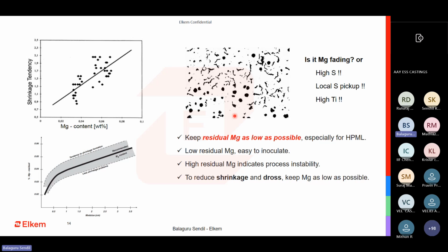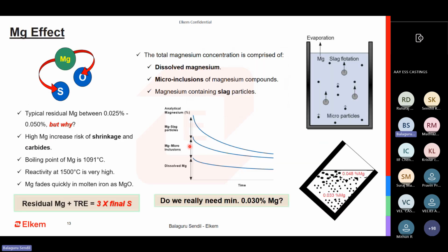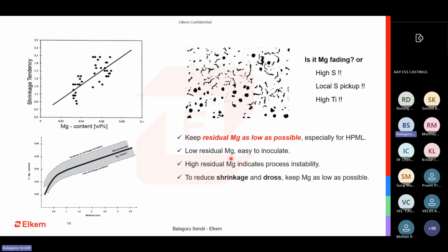It is quite stable. In the previous slide I showed, the micro inclusions are very stable, 1 micron in size. They do not fade with time. You just need to activate that micro inclusion, which is very small, like a small dot, to a very respectable size nodule of 20 to 50 micron with correct inoculation. So most of the time, when people complain that the magnesium has faded, 80 to 90% of the time it is because of sulfur, or sulfur pickup from sand, or the interesting reason, inoculant that has faded. This sort of microstructure is a very good example of inoculant fading.